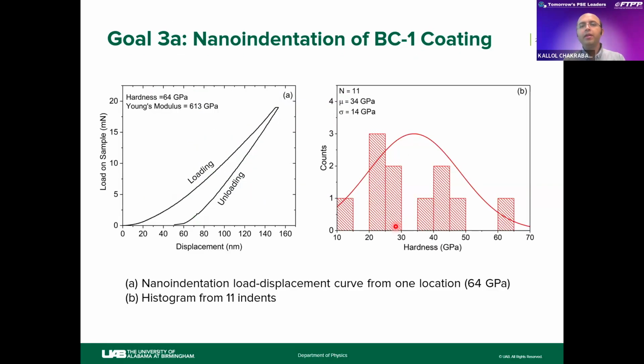As you know, our main goal was to synthesize a super hard material, so we definitely needed to check if our material is hard or not. That's why we did nano indentation, and according to the nano indentation, the mean hardness of our material was 34 gigapascal. There you can see so many indents were above the 40 gigapascal super hard mark.